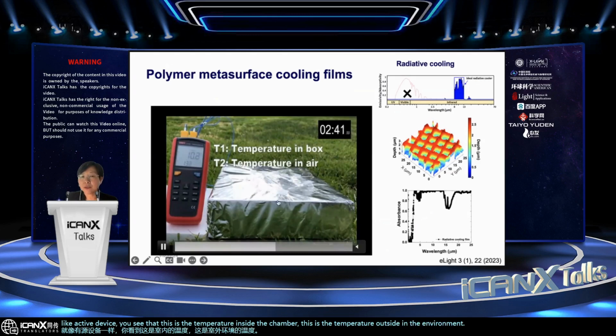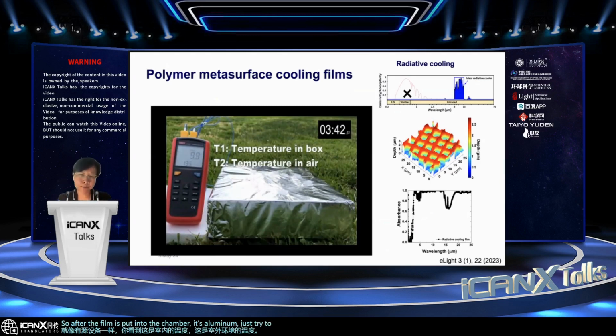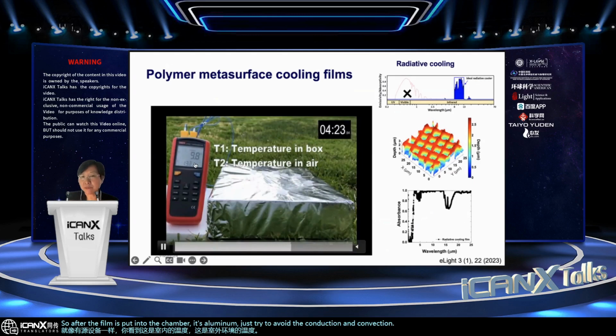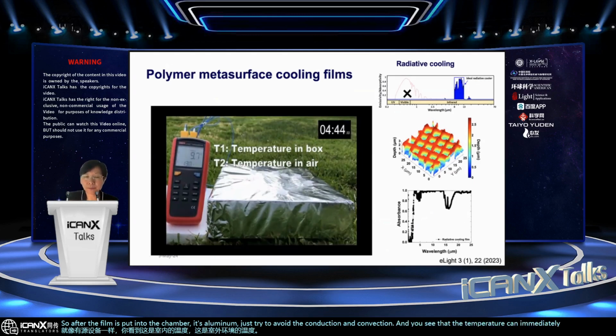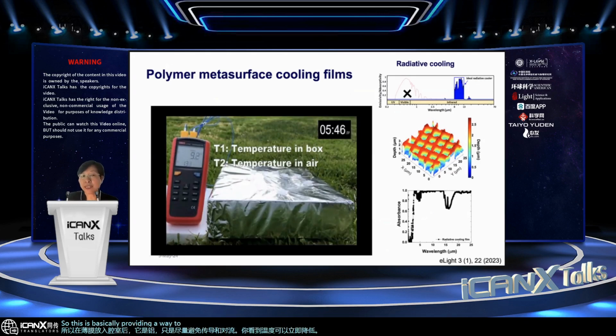After the film is put into the chamber, there is aluminum, just to avoid the conduction and convection. And you see that the temperature can immediately decrease. So this is providing a way to reduce the temperature without using any energy.